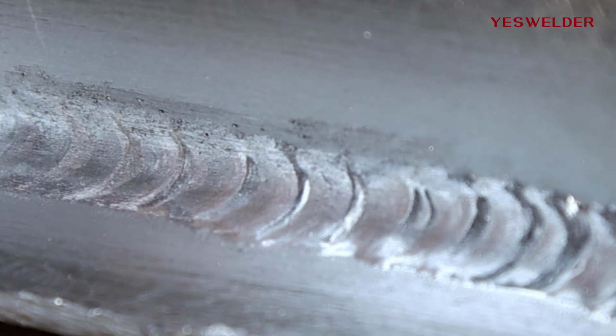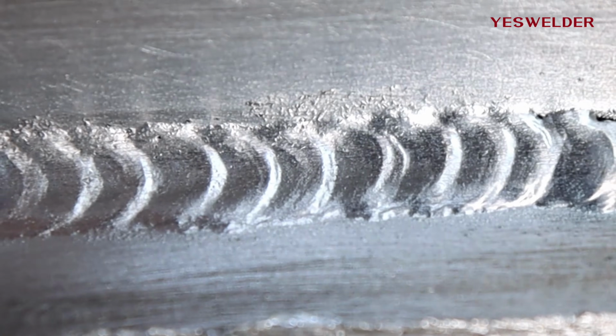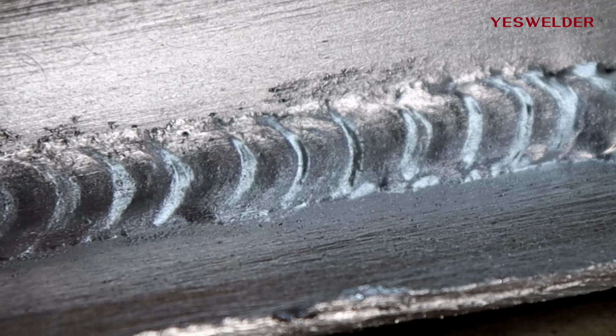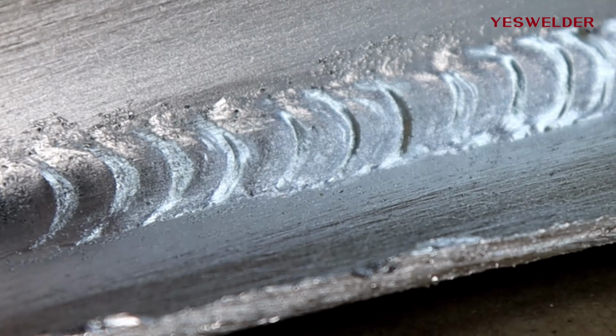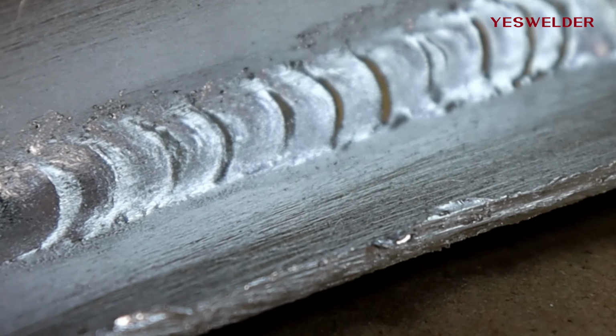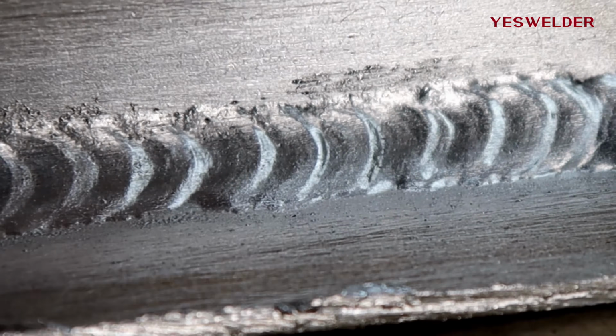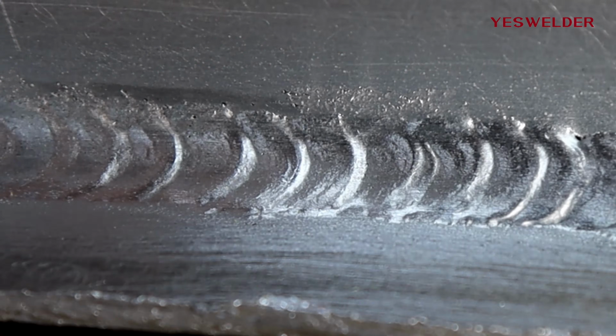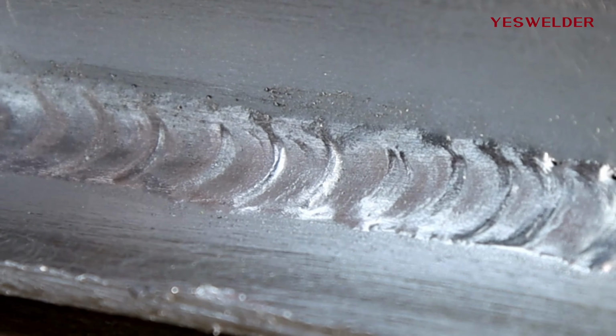Here's an example of spray transfer. You can see that the weld is more flat. That's because the weld puddle is more fluid and hotter. Also, the tiny ripples are gone and there's little to no spatter. That's because the arc stays on during the entire weld process.